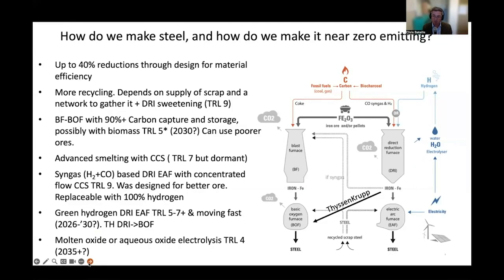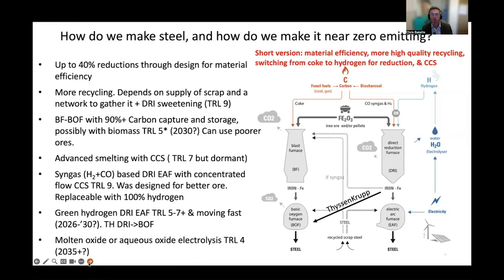But on just the base direct reduced iron, depending on the type of process that was built, we can also use CCS and potentially very high capture CCS. Moving out through time, beyond hydrogen direct reduced iron, there's potential to use electrolysis to directly separate iron ore, but we're probably looking at the late 2030s to early 2040s before we see a lot of penetration of that. Now, to make it simple, the short version is more material efficiency, more high quality recycling, get the copper out of the scrap, switching from coke to hydrogen for reduction, and CCS.